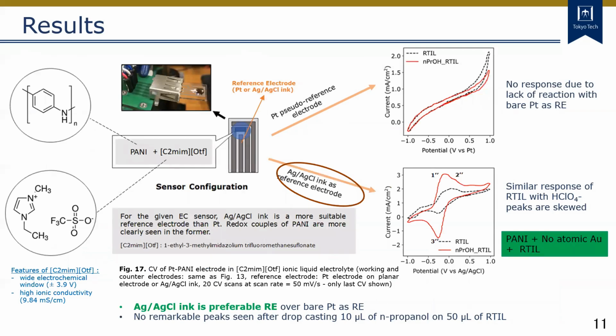Finally, the configuration of the planar electrode is also tested with room temperature ionic liquids as electrolyte. It is shown that once again, for room temperature ionic liquids, depending on the choice of reference electrode, the cyclic voltammetry is different. This response was confirmed for both pure ionic liquid and ionic liquid with n-propanol in a 5:1 ratio. For Ag/AgCl ink as a reference electrode, the electrochemical response is acceptable, although it appears as a skewed shape of the voltammogram with perchloric acid only.